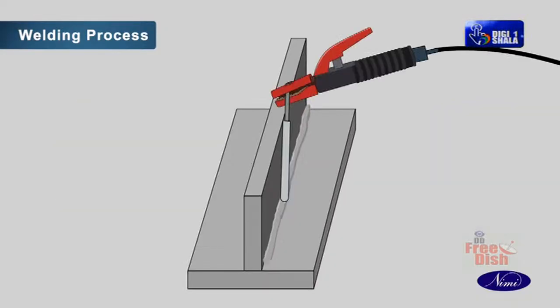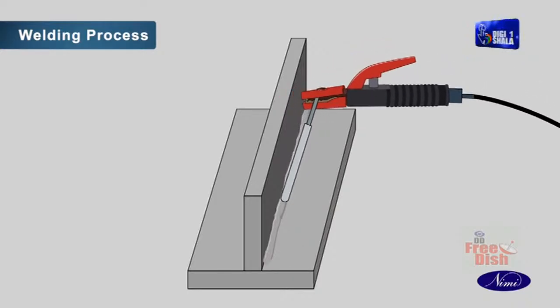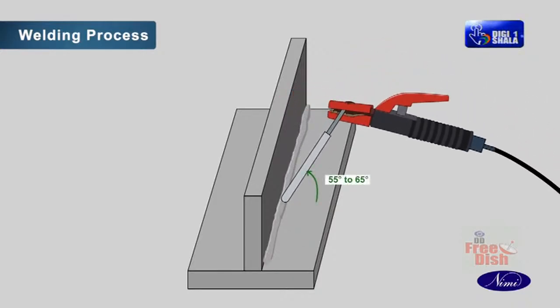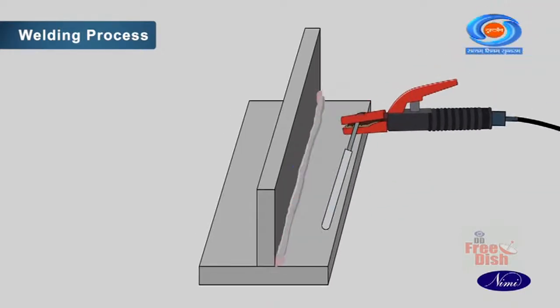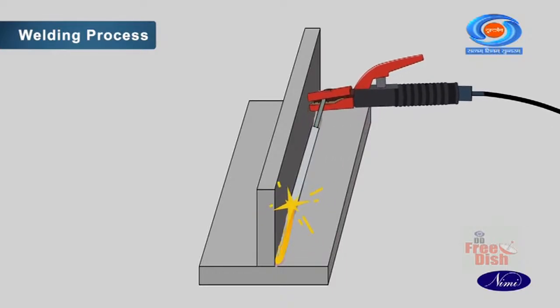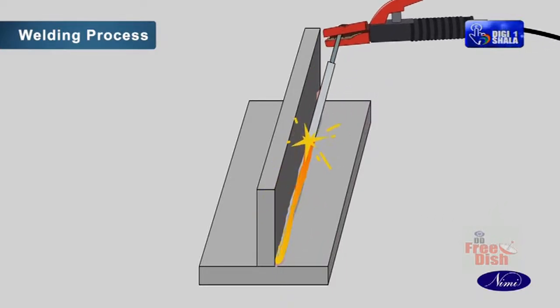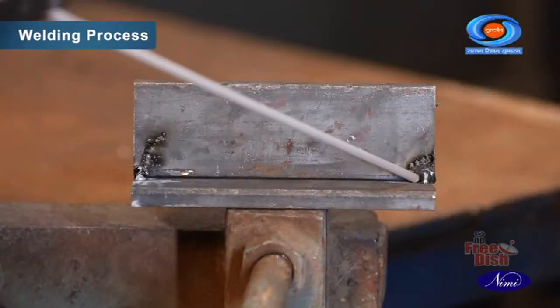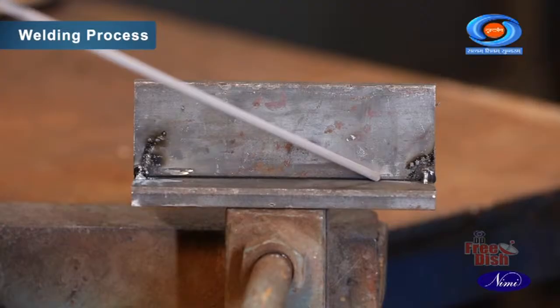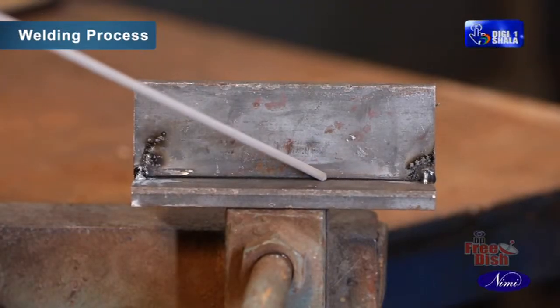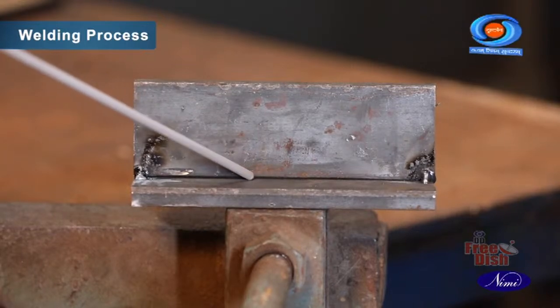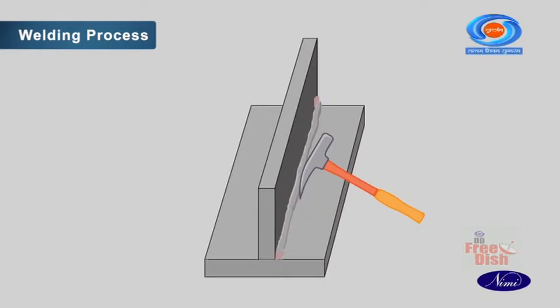Deposit second run with a 4 mm electrode and 160 amps welding current. The angle of electrode to the bottom plate has to be 55 degrees to 65 degrees and 25 degrees to 35 degrees to the vertical plate and 70 degrees to 80 degrees to the line of weld. The second run has to be deposited partly covering the root run and partly on the bottom plate. Give a steady movement to the electrode using a short arc. Deposit the root run in a straight manner. Avoid weaving movements. Deslag and clean the weld bead.